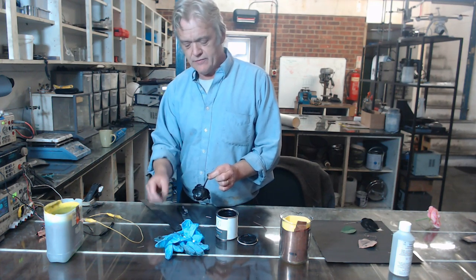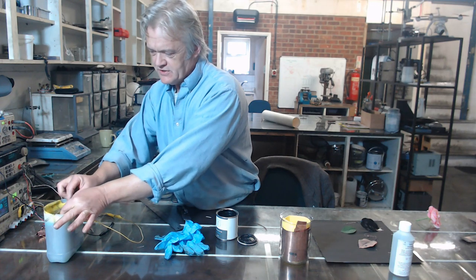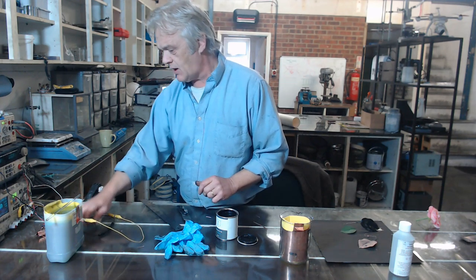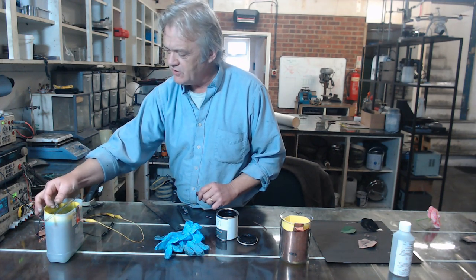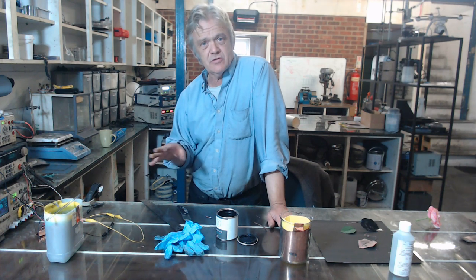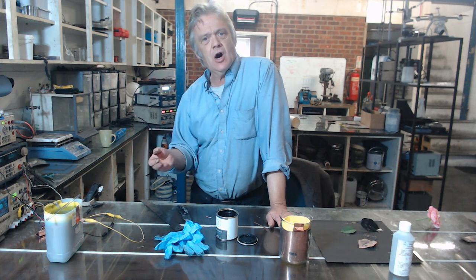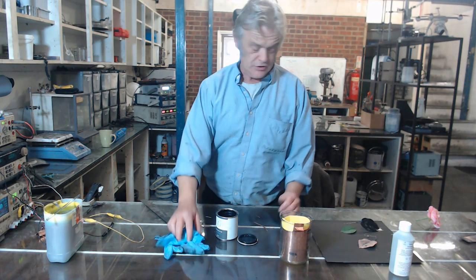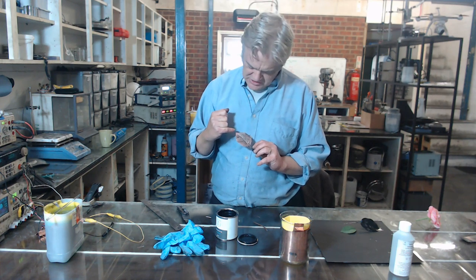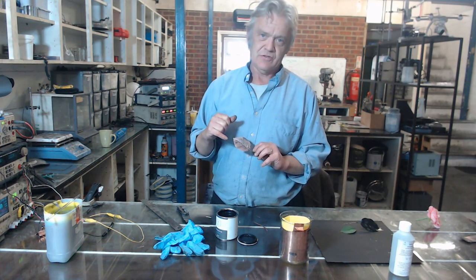I'll put a little twist in the wire and pop that into my universal plating solution. You can see I've got the copper attached to the positive, and the flower gets attached to the negative. Off she goes, plating — that's only at 2 volts, so it's drawing a very small amount of power. I'll give it 2 volts for about 12 hours and then turn it up, which prevents burning off. Here's a leaf that I started yesterday and you can see it's got a beautiful shiny copper coating on it. I need to give that about another 12 hours in the bath and then it'll have a lovely shiny copper coating.